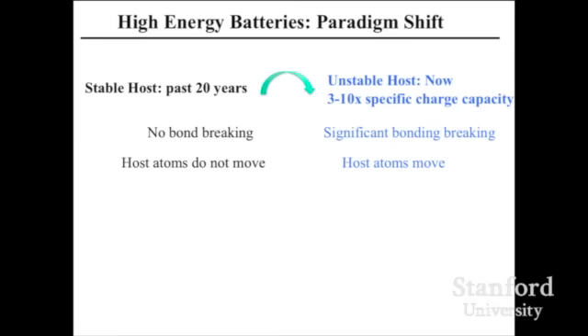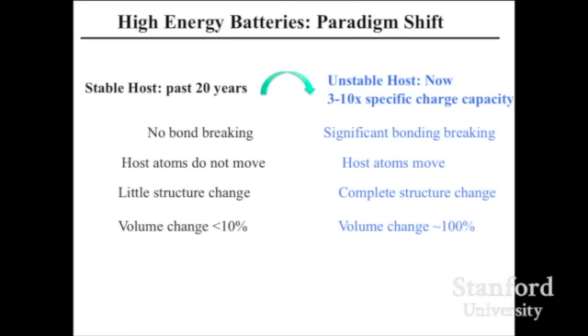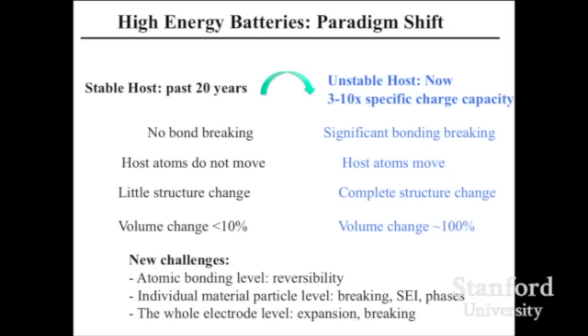There's possibly a lot of irreversibility build-up. And host atoms do not move on the left. On the right, host atoms are moving all the time. So once atoms move, the structure is not stable. It can collapse. There is little structure change on the left, complete structure change on the right. Volume change is less than 10% on the left, but it's really big on the right, 100% or more. So this presents challenges at the atomic bonding scale, the individual particle scale, as well as the whole electrode scale. How do you really make those materials work? The thinking needs to be changed.